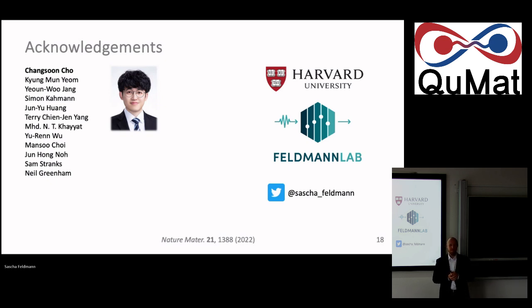Yeah. Can you explain a bit more how you determine this vertical diffusion constant? There's a lot of modeling. Yes, it's just a lot of modeling. So it's really just from all these individual measurements, from the distance-dependent measurement, we get more information about the diffusivity locally. From the just fluence-dependent time-resolved PL, we can get the trap density of the film. And then again, from the front and back side, we take into account photon recycling and self-filtering effects.